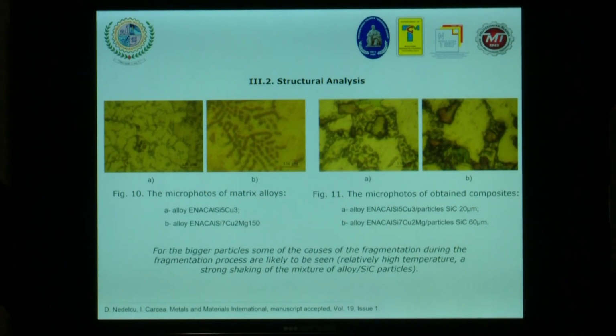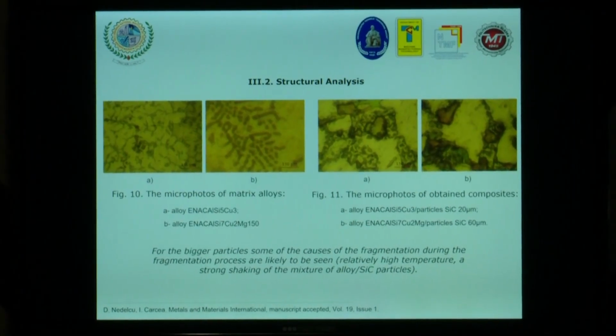Please, one small query. If you see, when compared to the base alloy, where you have dispersed particles, all the silicon carbide and rest of the particles are being agglomerated only at the grain boundaries, rather than within the grains. So, any particular reason for that? Because why I ask this is because this is a cast aluminum product. Do you do a stirring process while qualification?